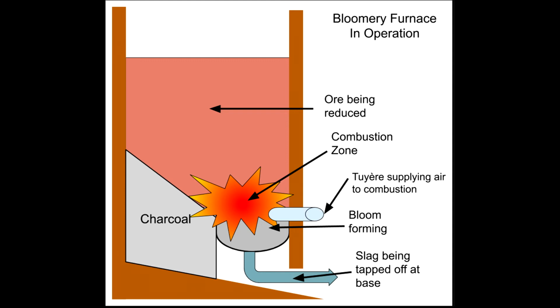In the Roman period, at least, this wasn't understood for the smelting stage of the process. I'm not sure when exactly iron workers realized that they could use limestone to deal with this, but iron oxide can also do the job. Exposed to enough heat, 2 ferrous oxide, which iron oxide will have in abundance because of the processes above, plus silicon dioxide, forms iron silicate. Alumina reacts much the same, but I cannot find the formula for the life of me. Of course, that means we lose a decent amount of our iron from having it serve in place of a flux, which further lowers our efficiency. Those new slag compounds melt around 1150 degrees Celsius, well below the melting temperature of iron.